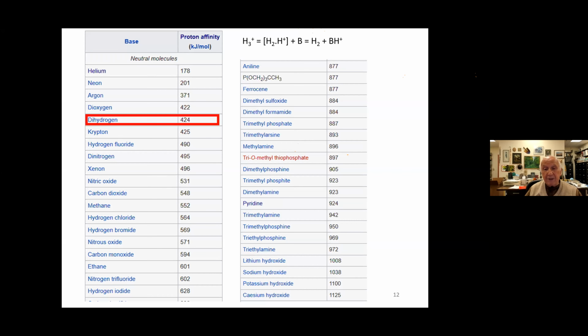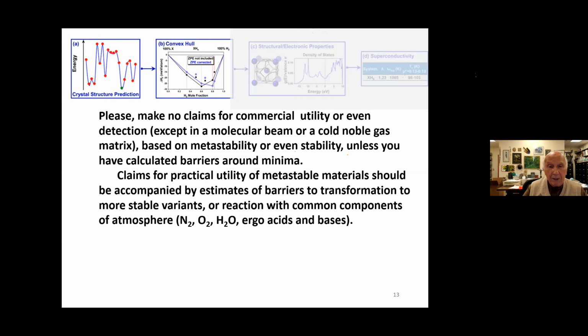Look down this list, for instance, for triethylamine. That's an amine, an ammonia. That has a proton affinity of almost 10 eV. If one of those amines encounters H3+, it's going to gain 6 eV by taking the proton away from H3+, from H2. So just because H3+ is stable doesn't mean that it's going to be there. So the moral here is, please make no claims for commercial utility or even detection except in a cold noble gas matrix or in a near vacuum molecular beam. Make no claims for commercial utility based on metastability or even stability.